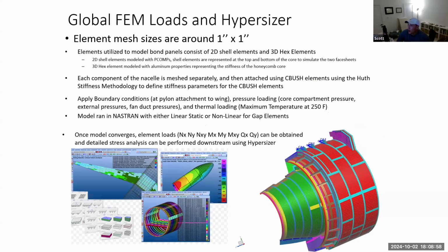Correct? Okay. So in terms of the nitty-gritty structural analysis substantiation, what we typically do is model the components in finite element software. And then we use other software like Hypersizer to calculate our margins of safety. So in this example, we mesh our components typically with 1-inch by 1-inch shell elements. Typically you use 2D shell elements with p-comp property definitions that represent the honeycomb core layup, the plies and the core, and then the plies on the other side. You could also use 3D hex elements to represent the core and then model the face sheets with 2D shells on top and bottom of the 3D element. Typically, the first option is utilized the most because it's easier in terms of FEM modeling.